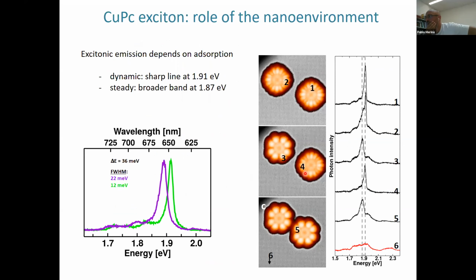I don't think so. No. I would say that these are all taken the same way, because you need to integrate. To get this, you go to a constant current on top of a molecule, and you integrate for 60 seconds typically, or 2 minutes, to get a good signal to noise ratio. And it strongly depends on the plasmonic envelope that you have when you measure. So here, I think it's only a matter that it's not properly normalized. But again, this you can change very easily by integrating more time or less time.